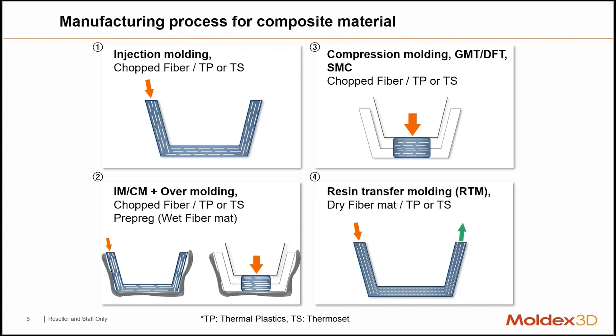For the majority of people in the plastics realm, injection molding is probably the most common technology for plastics molding in general. When it comes to fiber reinforced plastics or composite materials, we are usually injecting through one melt entrance or one gate on the part, and the fibers are oriented along the flow path for the most part. Unfortunately, that doesn't give us a whole lot of control over the fiber orientation, which makes it very difficult to control warpage, structural mechanics, and all those sorts of things on an injection molded part.